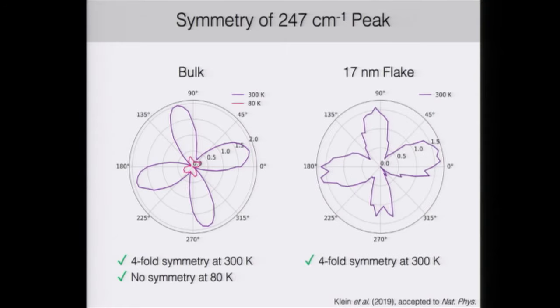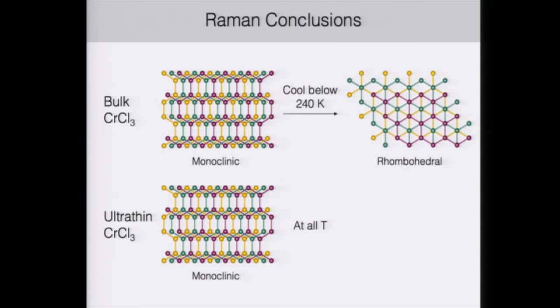In contrast, when we look at a 17 nanometer flake, we see this 4-fold pattern quite strongly at 300 Kelvin, and we still see it quite strongly even down to 80 Kelvin, well below the expected phase transition at 240 Kelvin. We've also measured this down to 10 Kelvin and see that this 4-fold pattern still remains in exfoliated flakes. Thus, on the basis of temperature and polarization-dependent Raman, we conclude that while bulk chrome chloride undergoes this stacking change from monoclinic to rhombohedral, ultrathin chrome chloride remains pinned in the monoclinic phase at all temperatures.